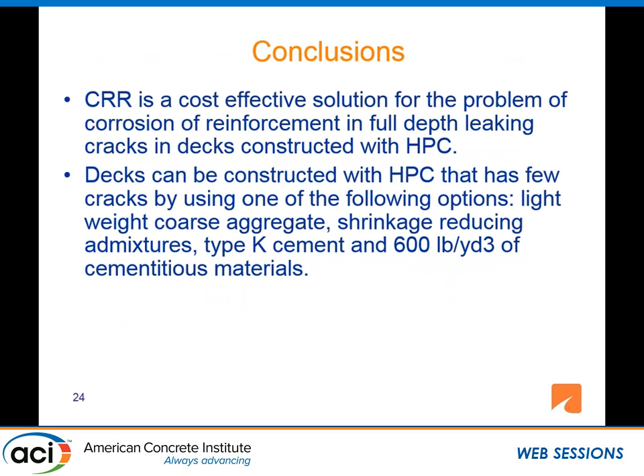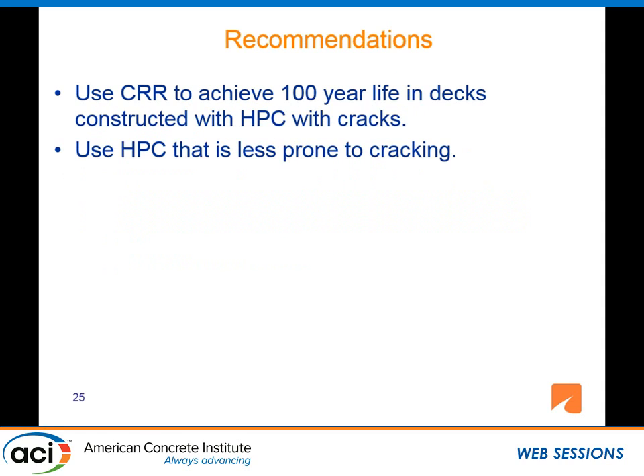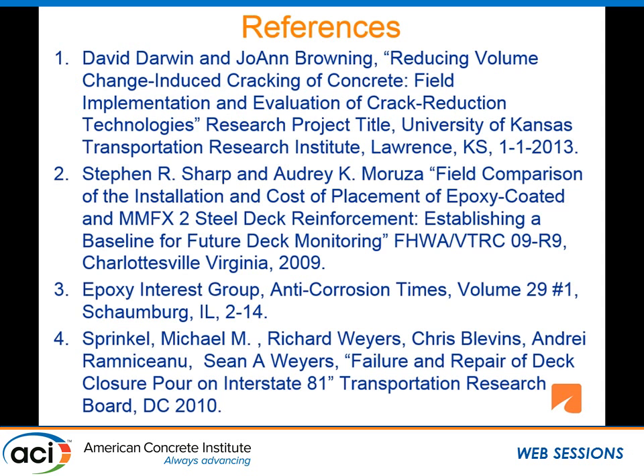So in conclusion, corrosion-resistant rebar is a cost-effective solution for our problem with corroding reinforcement and full-depth cracks. Decks can be constructed with high-performance concrete that has fewer and tighter cracks by using lightweight coarse aggregate, shrinkage-reducing admixtures, type K cement, and less cement. So we recommend at this time to continue to use corrosion-resistant reinforcement and try to develop mixtures that will be less prone to cracking. And these are the references that should be available to you if you want to download the presentation later. Thank you.